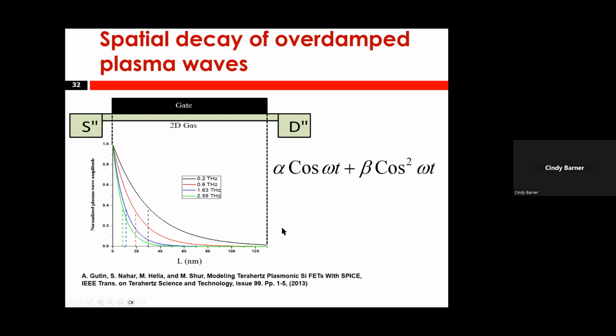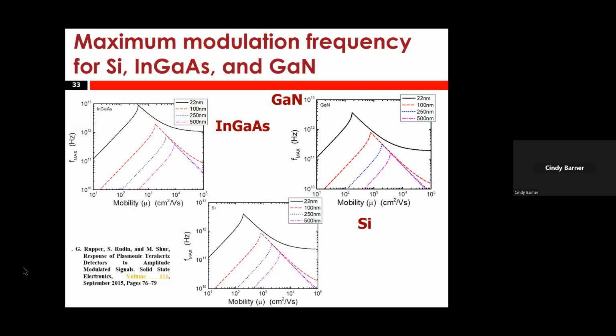And interestingly enough, that in terms of practical application, is as good or better than what is today in the market. So this is a really important mechanism. So anyway, we come to a conclusion that for detection, transistor is a very good device. And the problem mostly is how to achieve radiation out of it. But before that, I want to show the slide showing the maximum modulation frequencies as a function of mobility. And you see that in principle, optimizing the mobility value, optimizing scattering, and optimizing the size of the channel, you can reach terahertz frequencies of modulation. Huge bandwidth, which is good news.